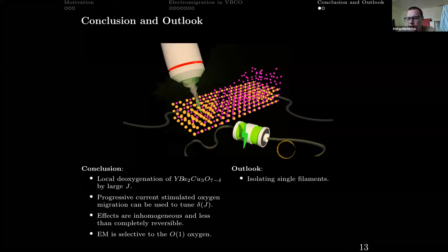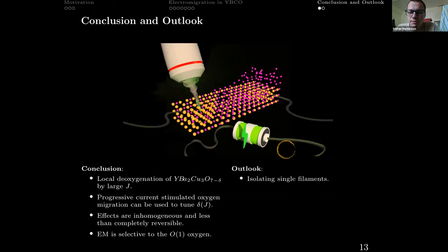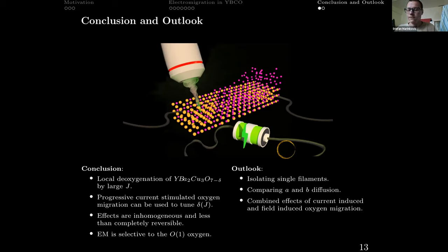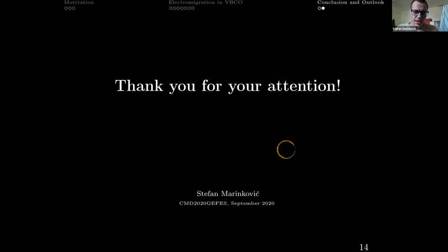We now would like to isolate a single filament, if we could make something that small, to see if we could make a completely reversible device by isolating a single filament. And we wanted to compare the A and B diffusivity of the material, because they have been known to be very different in these two lattice directions, and our films do not distinguish them. We could combine the effects that we find with the findings of, for example, Anna, and work on something that would combine the effects of field-induced and current-induced oxygen migration. And we could compare similar materials like other perovskites or other cuprate superconductors. With that, I would thank you for your attention, and I will answer questions.